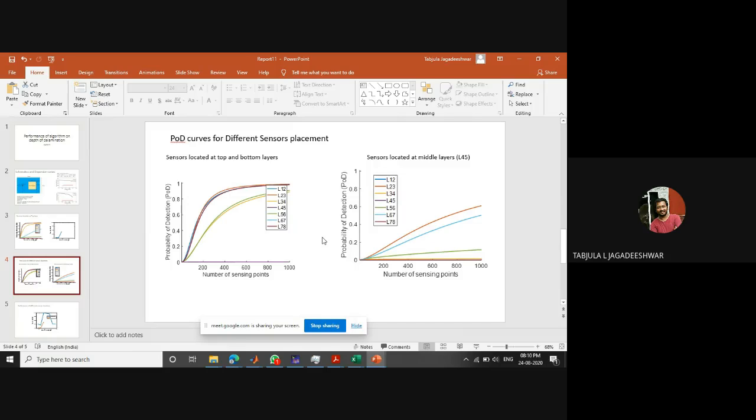It is coming from the domain side itself, because delamination in 4 and 5 is actually creating two equal halves. That means the impedance mismatch is not that great there in order to trap the energy. So it simply allows the wave to pass to the other end. That's the reason. Our algorithm is actually based on energy trapping instead of calculating the reflection.